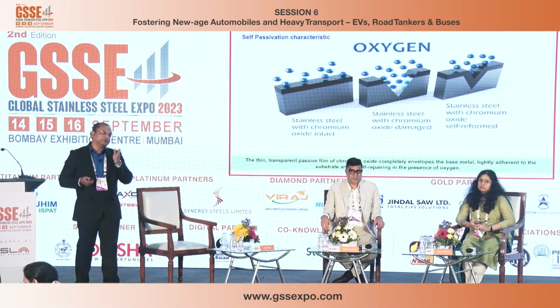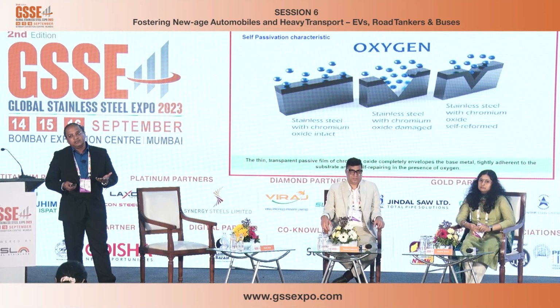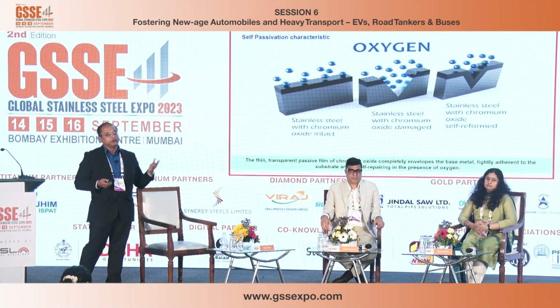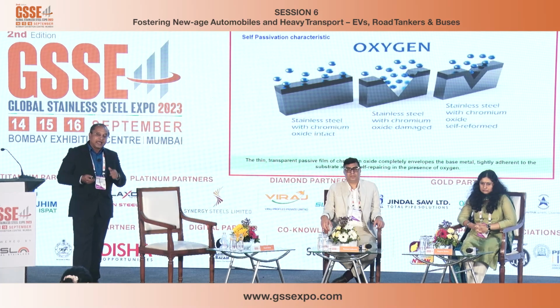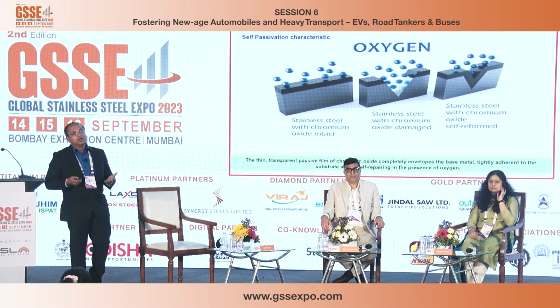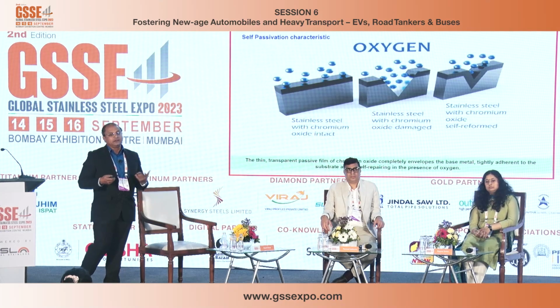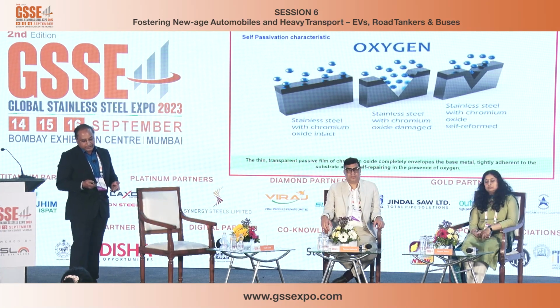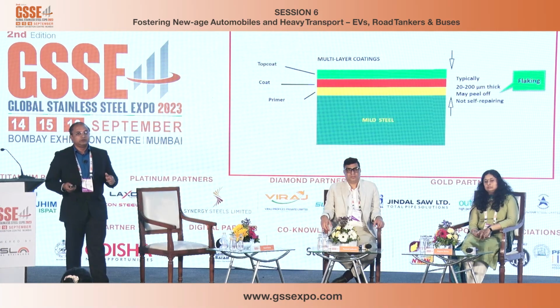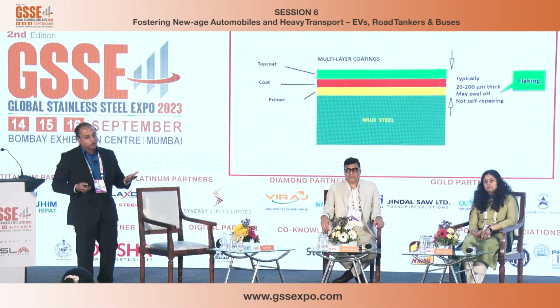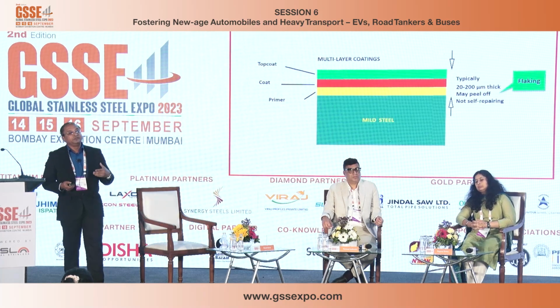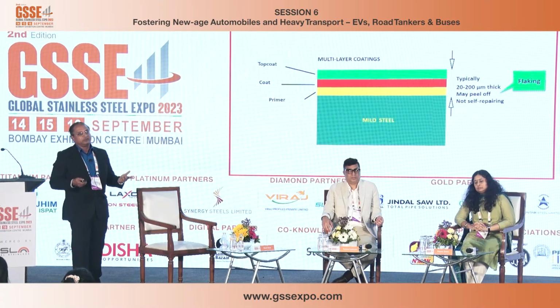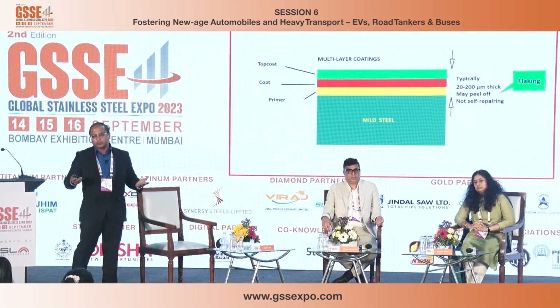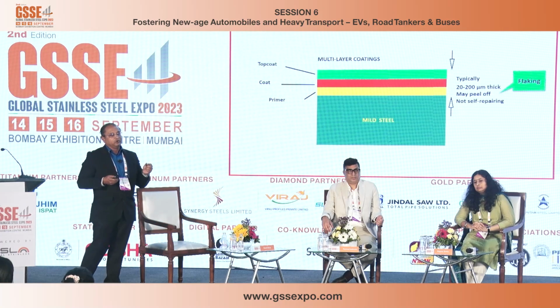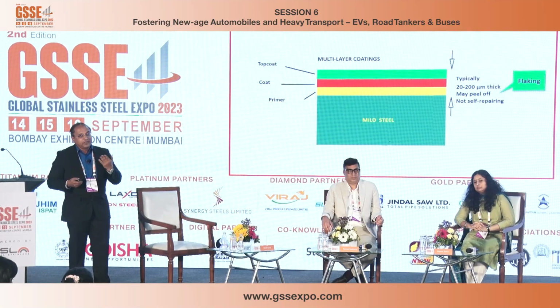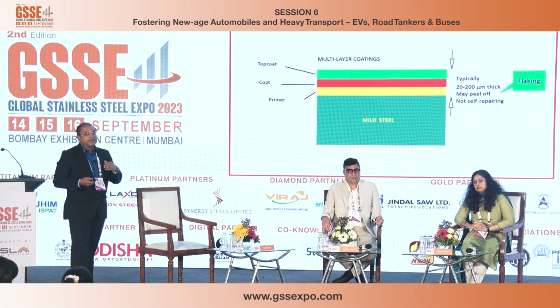Even if the film is broken, immediately the chromium from the metal reacts with the surrounding oxygen to reform this chromium oxide layer. And that is the reason why the durability, the longevity with stainless steel is significantly higher as compared to galvanized or a painted material. In galvanized or painted material, you either have a zinc coating or paint. Both are physical coatings. And therefore, normally during any kind of bending operations, forming operations, welding, from micro regions, the zinc film or the painted film peels off.